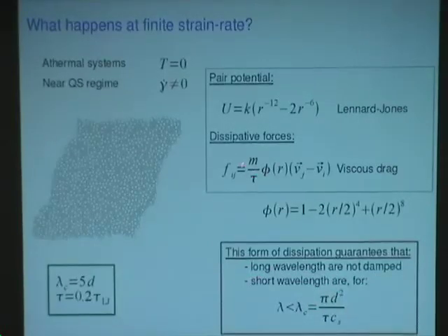In fact, there is a damping parameter which essentially sets the scale at which you damp the sound waves. Here we choose this scale to be of order a few particles, which means it's of order of a zone size. Yes. You cut that off at distance 2, which is the distance of the interaction potential, at the cutoff of the Lennard-Jones potential.